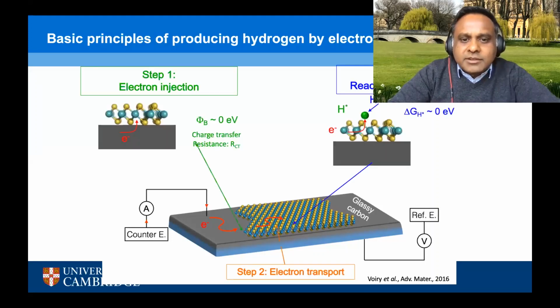And so in the case of hydrogen evolution reaction from electrocatalysis, the first step in the reaction is this charge injection from the counter electrode to the catalyst. And this charge injection, in electrochemistry, is often referred to as charge transfer resistance and other things. And this really influences the reaction kinetics of the electrocatalysis. But we view this as contact resistance, and over the years we've worked on how we can reduce this contact resistance using the things that we learned for our FETs to boost the electrocatalytic performance of these materials.